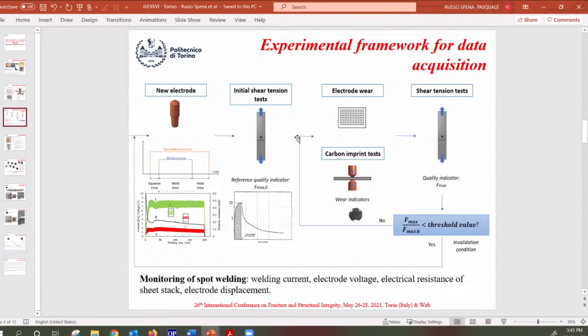Particularly, the electrode wear was defined through a carbon imprinting test that, as you can see in the following, allows us to approximately identify the extent of the electrode wear. At the beginning, we performed some spot welds with new electrodes and an initial shear tension test. After that, we performed a series of weld spots, and after a certain time we defined the corresponding mechanical properties. We repeated this operation over time and defined the effect of electrode wear on the mechanical properties of the spot welds and the fracture mode.